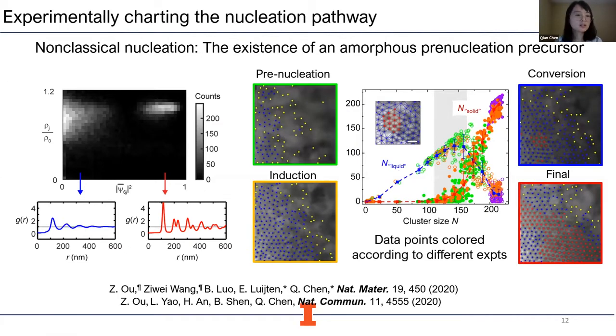So this non-classical nucleation is also verified in our real space snapshots. You can see the red crystallized cells only start to form as the blue amorphous domain grows to a critical size. And this is repeated, so we collapse the data for multiple movies into this one single master curve. In a later work of ours, we are able to calculate the kinetic nucleation barrier, which is indeed lowered in the presence of this amorphous pre-nucleation precursor. So this is our understanding of nucleation pathway at the nanoscale.